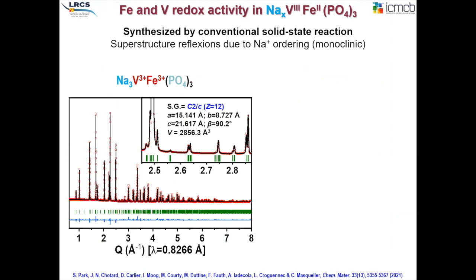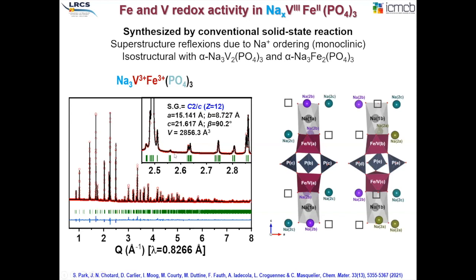Besides this manganese substitution, we worked actively on the iron type of compounds, and we first prepared this new compound, Na3 FeV PO4 three times. So it's rather easy to prepare, but the crystal chemistry is not that trivial, and it shows, as many sodium-3 containing materials, very nice sodium and vacancy ordering that leads to a very complicated superstructure with a huge unit cell and monoclinic distortion. So we prepared this material easily, and we tried as well then to prepare the Na4 FeV compounds